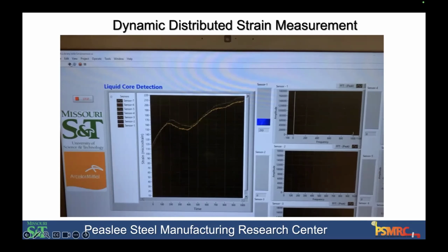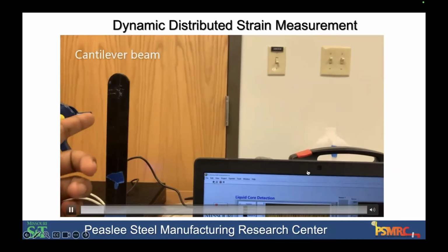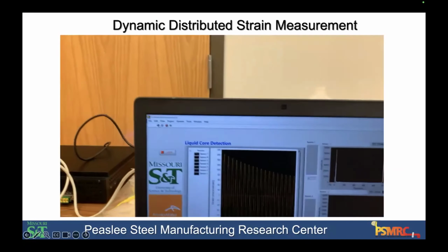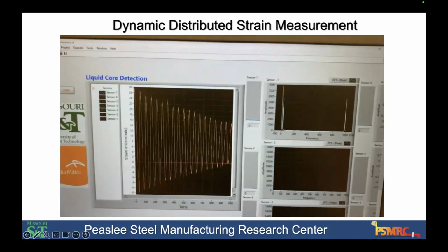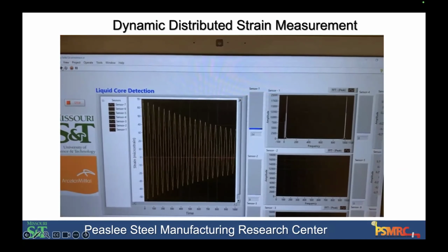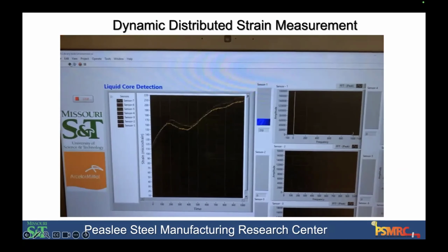So I was going to mention this one slide that I put up here that shows the vibration. One of the things that we've been able to do is use optical strain gauges on continuous casters and daisy chain the sensors on each roll location in the caster. And because you can daisy chain these, you can instrument a whole bank of rolls with one fiber. And we have successfully been able to detect the position of the liquid core in the machine by the ferrostatic load shift and its effect on the support structures. So you can see a deflection when liquid core passes under a particular roll set.